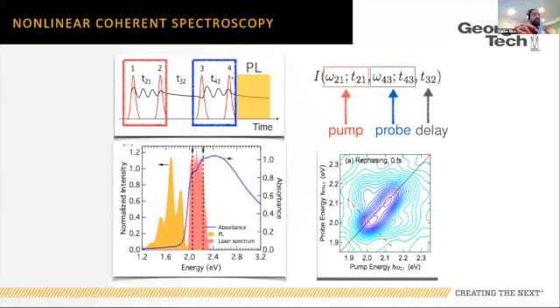I then excite to a 4th order population that I detect through photoluminescence, and I can demodulate that with a lock-in amplifier, knowing very precisely what the phase relationship is of the signal that I'm measuring, and I can construct a nonlinear signal that way.